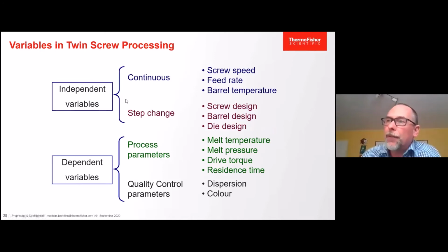From these independent variables, we will now see that melt temperature depends on the different variables we have set before. The melt temperature, temperature as well, the melt pressure, highly depending on the feed rate. Drive torque, of course, residence time is influenced by screw design. And from there, we get parameters like how good is the dispersion, how good is the compounding, or how good is the color concentration or the color distribution, the pigment distribution inside a masterbatch, for example.